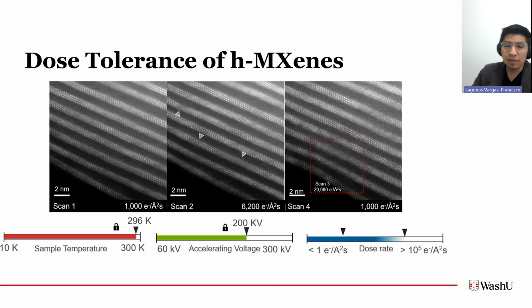We can see that if we give it a lot more dose, so in this case, 6,200 to 20,000 electrons per angstrom squared, we start seeing this modulation in the Ti3C2 layers, which I marked by those little arrows. And this is kind of the first sign that we're really starting to damage the organic surface groups. And then as an effect, the MXene lattice itself is starting to deform. And we can see that seen a lot more significantly at very high electron dosages.